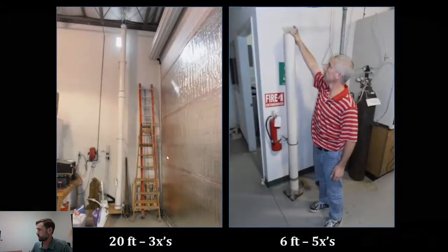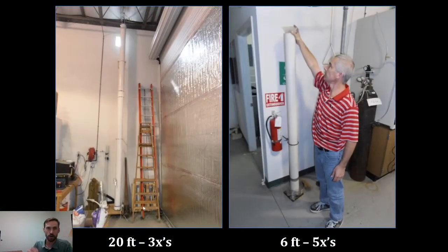So we actually test this in a lab. We use what we call a drop test, where we take a Polyon sample after it's been manufactured, and we drop it either 3 times from a height of 20 feet, as indicated by the photograph on your left, or we drop it 5 times from a height of 6 feet on the photograph on your right. And what this mimics is a possible disruption through the shipping channels, through the handling channels of Polyon before the time that it reaches you.